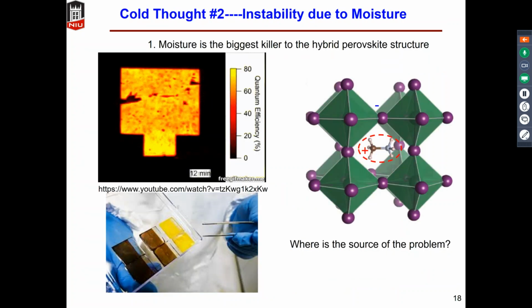Okay, so the next thought we had over perovskite solar cells was its instability, especially due to moisture. And this is a video clip I got from YouTube. As you can see, within 30 minutes, the perovskite layer will suffer degradation by moisture. And this is the fluorescence image of this perovskite thin film. After 30 minutes, it becomes the characteristic yellow color of lead iodide.